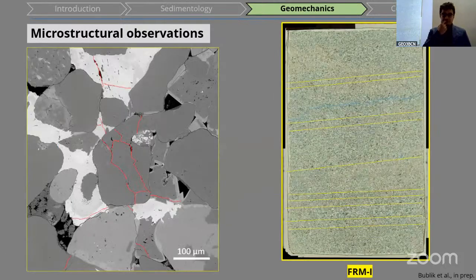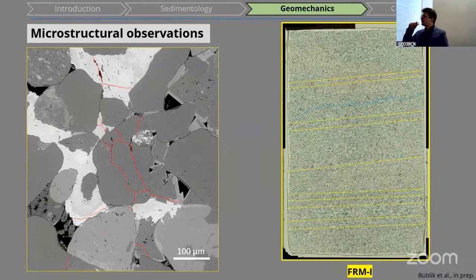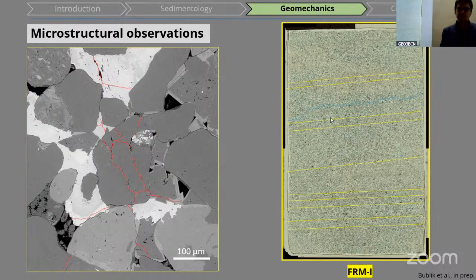Now, if you look into the sample in more detail, what you can actually see is that the cementation is very much layer-based, similar to what we've seen on the shortwave infrared photo, where you have every couple of millimeters a high or low carbonate content. This is what you observe here in the thin section as well. So you can see some layers are very strongly cemented and others are more porous. And what we try to understand at the moment is how does this layering actually impact compactional behavior?